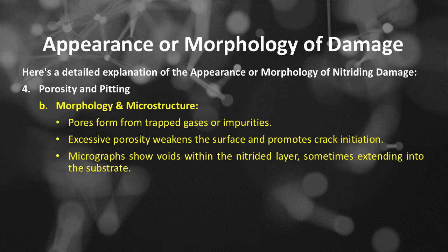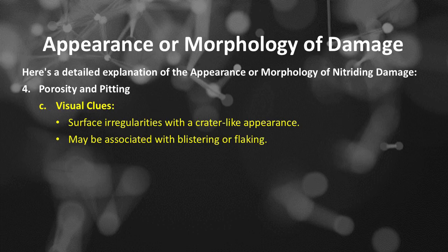Porosity and pitting morphology and microstructure: pores form from trapped gases or impurities. Excessive porosity weakens the surface and promotes crack initiation. Micrographs show voids within the nitrided layer, sometimes extending into the substrate. Visual clues: surface irregularities with a crater-like appearance, which may be associated with blistering or flaking.